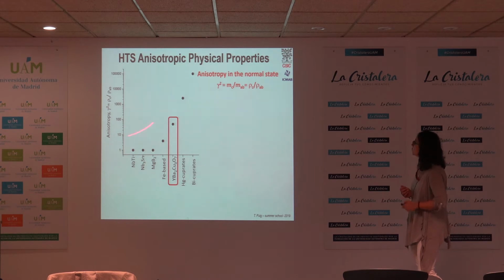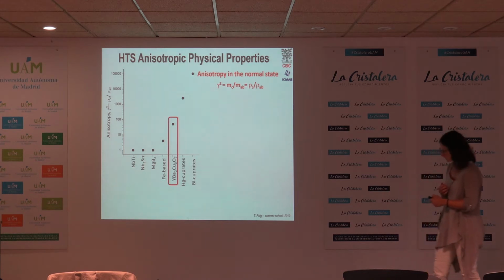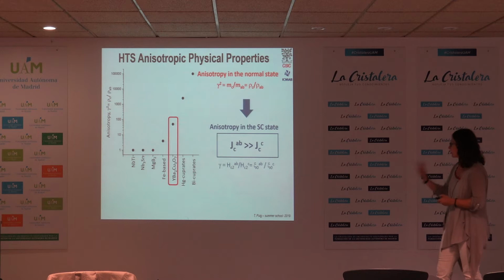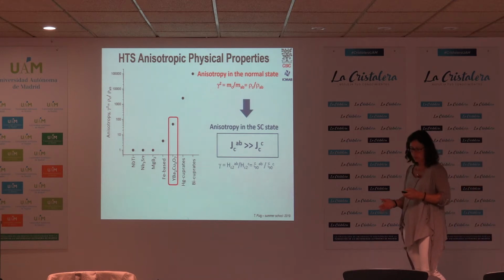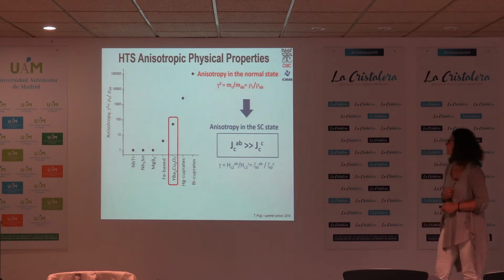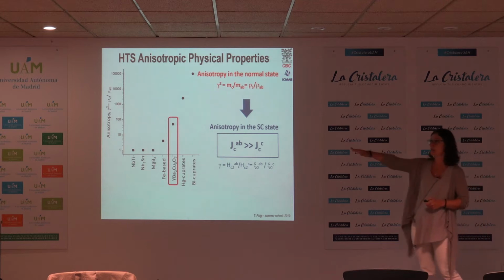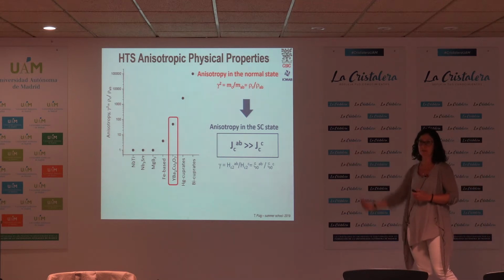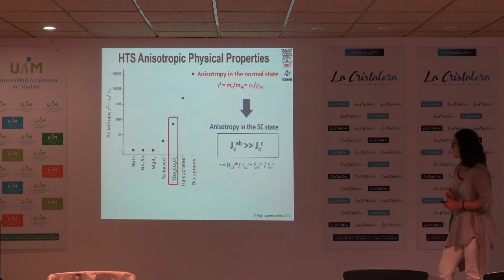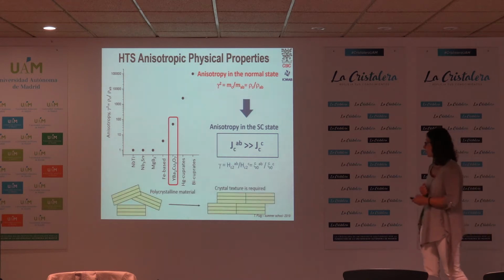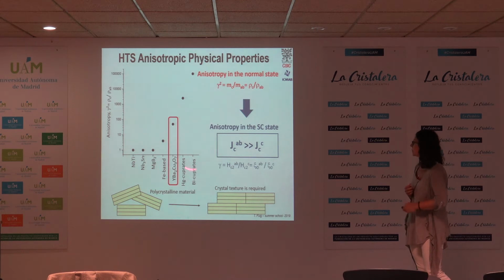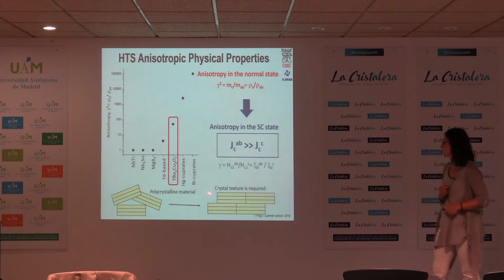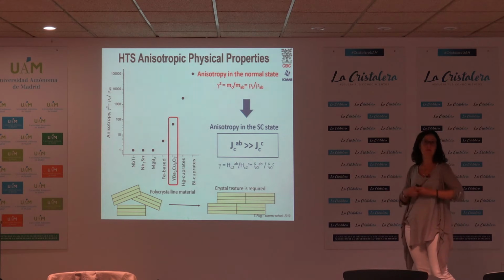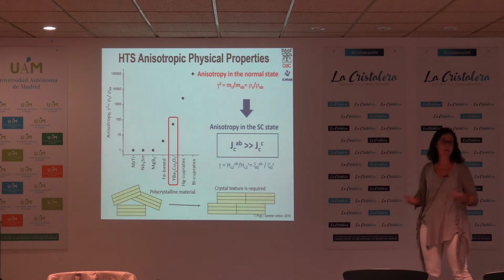This would be the anisotropy in the normal state, but that also transforms to the anisotropy in the superconducting state, so that if we pass current along the AB planes, we can pass a lot of current, but if we have to try to pass current along the Z-axis, that goes very small. And therefore, that means that these kind of materials, these highly anisotropic materials, we cannot just produce them in a granular material, we have to do thin films. So we have to do epitaxial growth.